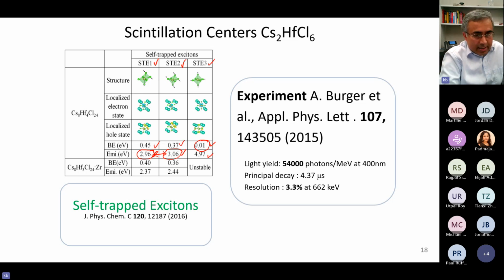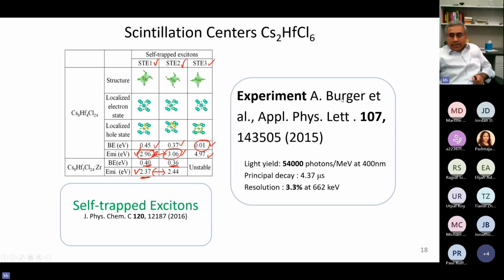And then for the case of zirconium, we found a different emission energy of 2.37. And the zirconium is also stable. You see, it also forms structures similar to STE1 and STE2, and they're also stable, and their emission energies are also very similar. However, between hafnium STEs and zirconium STEs, the numbers are different. Okay, so it matches up with what A. Burger and their collaborators did back in 2015.